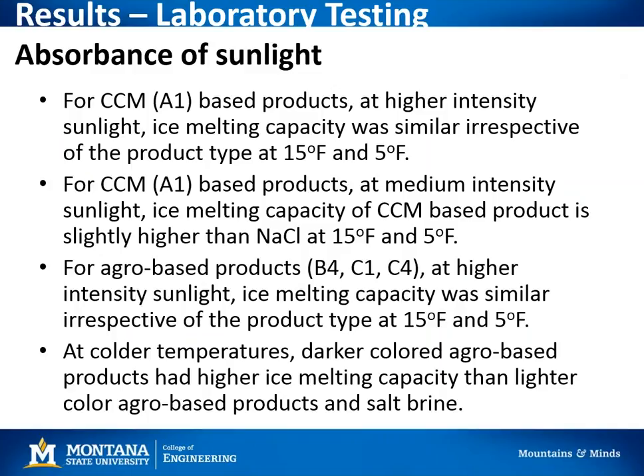So in summary, for complex chloride mineral-based products, with higher intensity sunlight, which is the direct UV exposure, the ice melting capacity was similar regardless of the product type. One interesting thing that we found with this test, it was the first time we had ever done it, is that even though the environmental chamber had very tight temperature control, the location of the sample placement was influential. The sample that was directly under the UV light had more melt than if it was on the outside of the exposure to the light. So we basically shifted all the samples multiple times and collected data multiple times so that hopefully we would even out this exposure. But what we realized was that we could categorize the ice melting rates by high intensity exposure and then medium intensity exposure. And so that's kind of what we're getting at here.